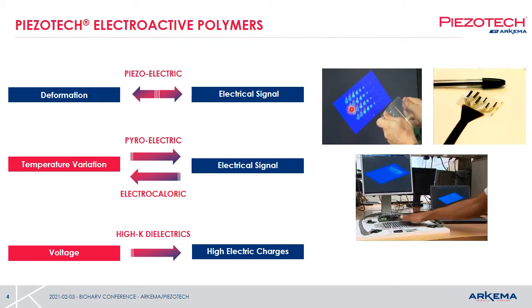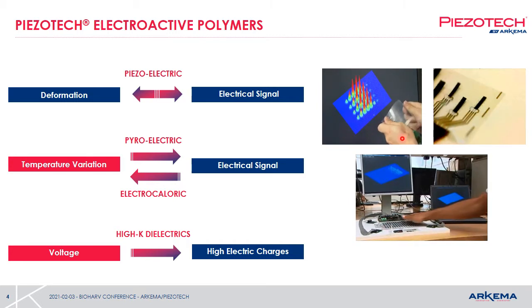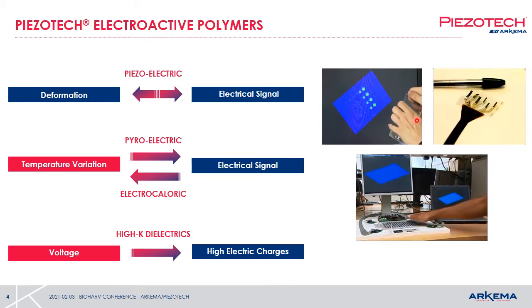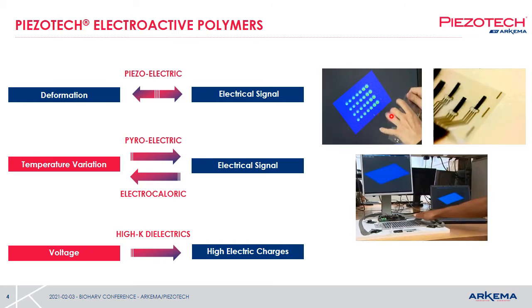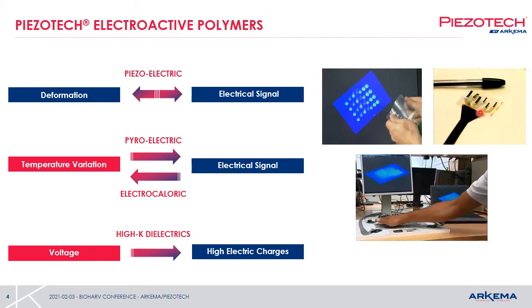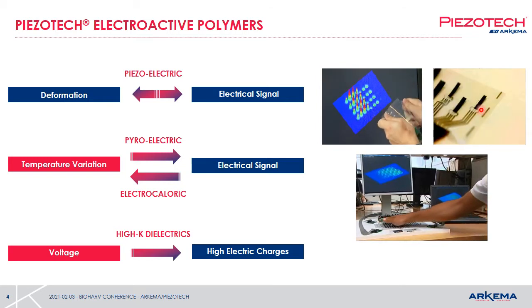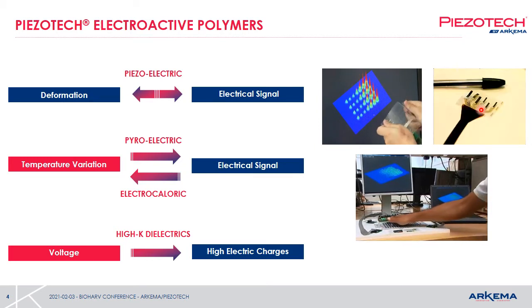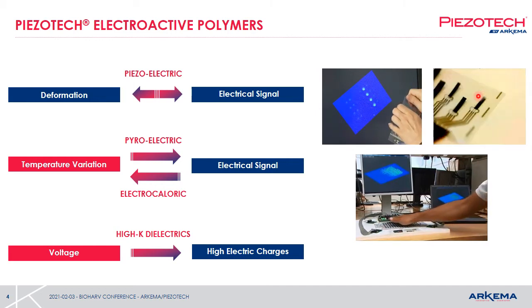On the top left video, you see printed piezoelectric arrays on a PET foil, almost transparent, and you see when you bend the polymer foil, you're able to detect the bending thanks to the piezoelectric layer. On the top right video, you have an actuator video, so you have a multi-layer of piezoelectric polymer, electrode, piezoelectric polymer, electrode. And when you apply an alternating electric field, the polymer layers are able to contract and give this actuation effect at the frequency of the electric field.